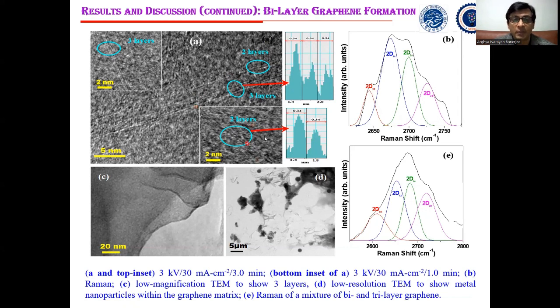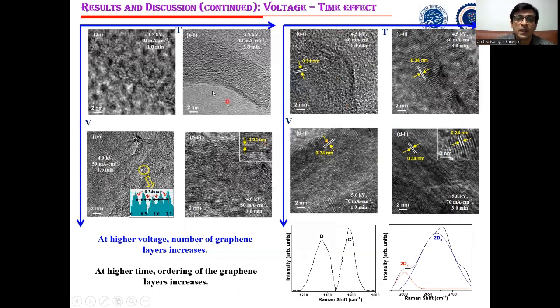Now, when we increase the sputtering parameters slightly, we are able to obtain some 3-layer graphene. Here also we are able to see all the 4 components of the 2D peak, but the intensity is decreased. So this is obvious, because when we increase the number of layers from bilayer to multi-layer, the 4 components will ultimately merge into two components, which is observed in this multi-layer graphene, where we increase the sputtering parameters, either the sputtering time or the sputtering voltage. So we are able to obtain multi-layer graphene, and this is showing the typical 2D spectra of multi-layer graphene, which is actually composed of two components.